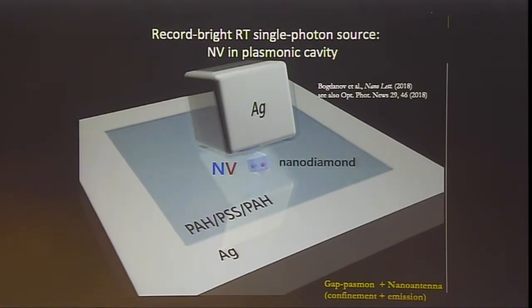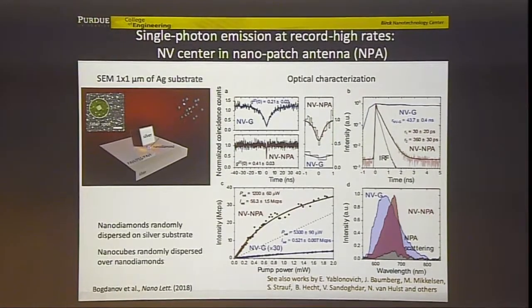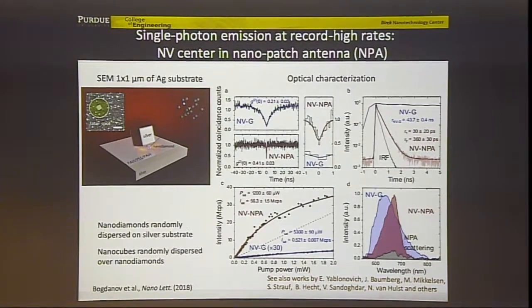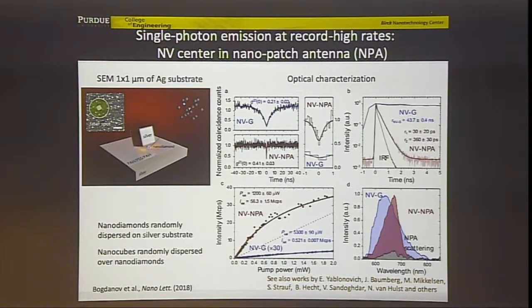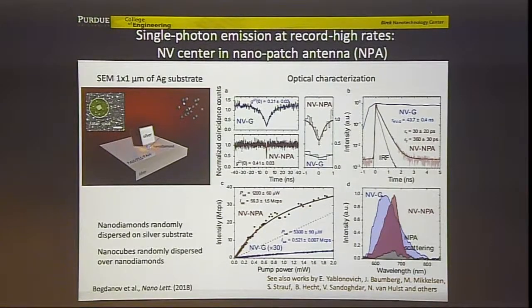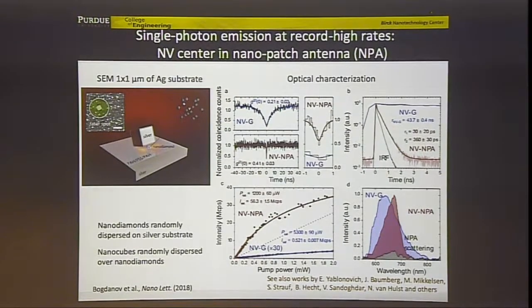So, and then the trick, then it works. That's the first result we obtained. To prove that we are dealing with single photon generation, we do this correlation function measurement, the G2 function. This is the standard way. What we obtained at room temperature: we first randomly distribute these nanodiamonds on a silver film, then randomly distribute these cubes. In some cases, just accidentally, a cube sits atop a nanodiamond.